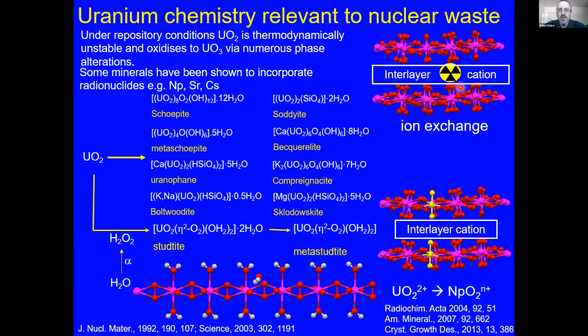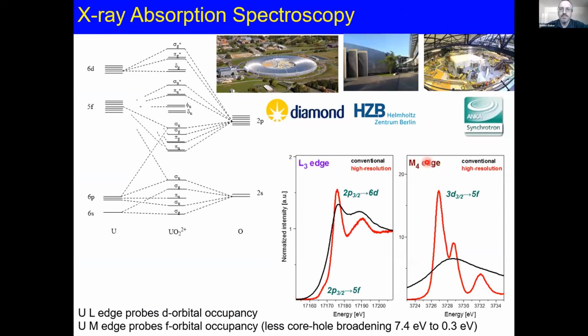Now, these minerals can incorporate radionuclides. For example, becquerelites could exchange calcium for strontium, radiostrontium, or radiocesium, or neptunium can be incorporated into the interlayer cations, or even into the sheet structures. So this might show ways of retarding mobility or migration. So we can use X-ray spectroscopy, hopefully, to take advantage of the fact that we don't need very much of our radionuclide materials to look at exactly what happens. To start off with, we really want to benchmark our studies on the basis of the natural minerals.